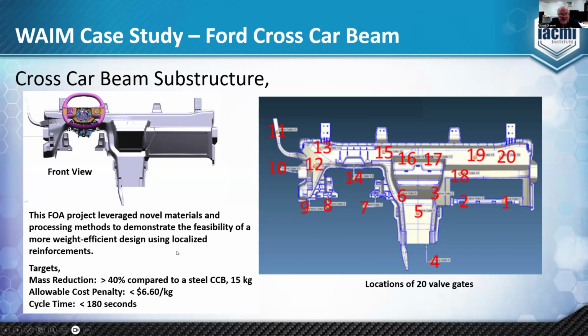The targets for the program were a mass savings of greater than 40% compared to a conventional steel cross-car beam, which for Ford typically comes in at 15 kilograms. The allowable cost penalty, again, because we're actually doing more functionality than a conventional steel beam, right? So you're adding cost, at the hope of saving mass and production cycle time. So the allowable cost penalty was to come in under $6.60 per kilogram, and we were targeting a cycle time of less than 180 seconds.